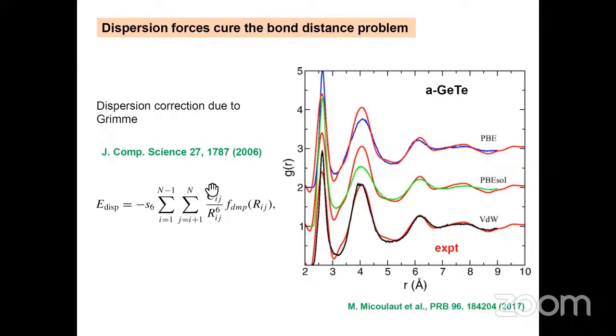I should remind you that these coefficients that you can see, Cij, including the damping function, can be either obtained from tabulated data, which correspond to gas phases, or they can be directly calculated, for example, from maximally localized Wannier functions. So here are the results for amorphous GeTe. Here is a PBE first result, which doesn't use those Grimme dispersion corrections, and you see that the agreement is not that good. It's also true for the alternative exchange correlation functional. And as you use that green curve and you switch on the van der Waals or dispersion correction, you see that everything now maps very well on the experimental red curve.